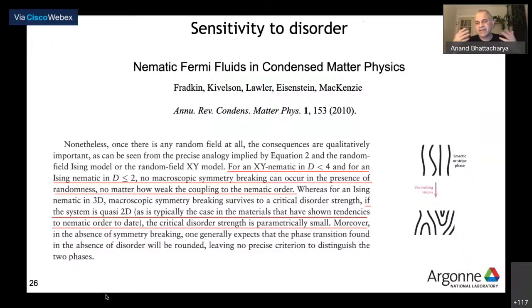So we began thinking about this. Why is it that it's sensitive? For example, it happens at low carrier densities, it happens at higher mobilities. It turns out there's some literature going back a long time saying that this nematicity, when it does occur in two dimensions particularly, is very sensitive to disorder. As in many things in two dimensions, a very small amount of disorder can break these nematic things up into domains. So as you make the sample dirtier, as you can measure in transport, it's going to stop being as nematic as it would have been had it been cleaner.